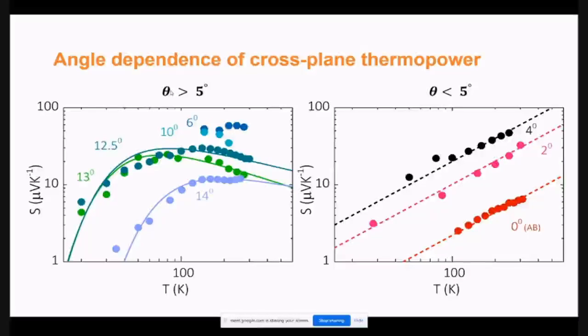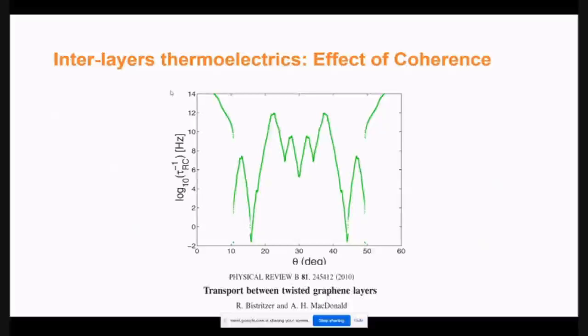Whereas if the angle between the two layers is smaller than 5 degrees, then we recover what you have as Mott law, in which the thermoelectric power is directly proportional to temperature. And we believe we understand this now. If you take two layers of graphene, this was the old theory of Bistritzer and MacDonald, and essentially it models the two graphene layers as an RC time constant, in which you calculate the tunneling probability of an electron from one layer to the other as a function of the misorientation of the two layers. It's just plain and simple calculating the hopping matrix element between two layers.